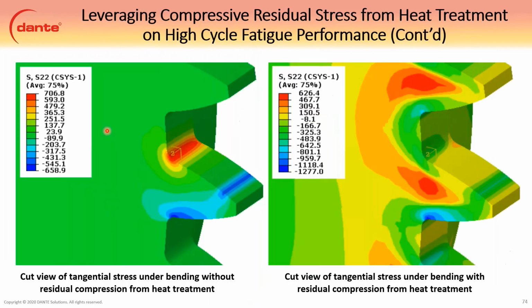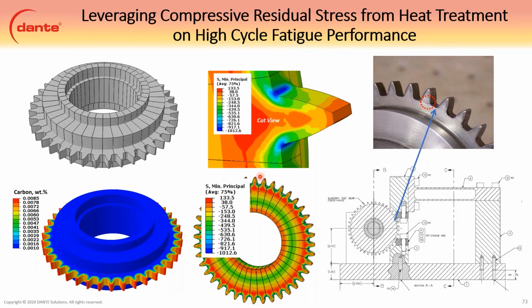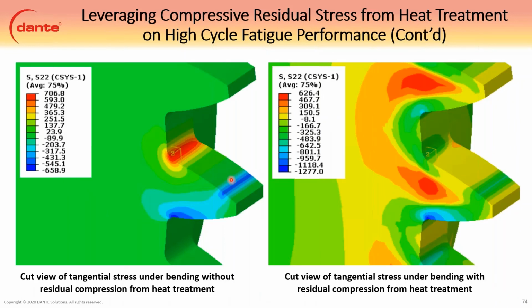I just want to show this real quick. We're running out of time here. These are test gears that we were modeling and using different processes to induce different residual stress magnitudes. This figure shows on the left a loaded gear, loaded out here on the tip. If it's loaded without residual stress, we end up with a tensile stress of about 700 MPa in the root fillet. If we do include the residual stress from heat treatment, we're still in compression. These are completely different scenarios. The one on the right says we will never fatigue out here because we never go tensile, where our mean stress is compressive.